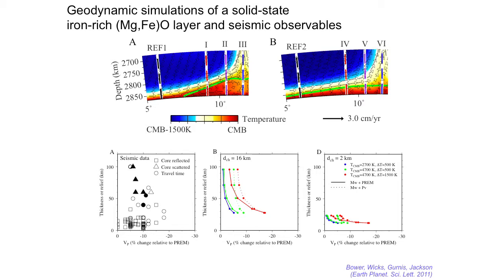And so that's a very interesting result, because we didn't expect such low velocities for a solid material at pressures of the core-mantle boundary. So these are extremely high pressures, 1.4 megabars, and it's still a very, very soft material. And so we have a great match to the observables.